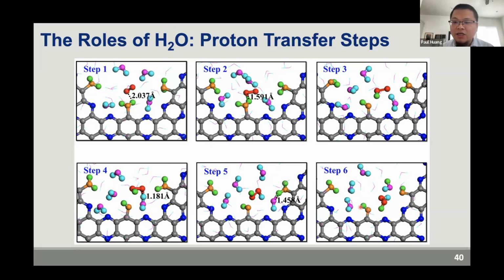And for that reaction, they have to involve 2 adsorbed water, and some local free water molecules will help to speed it up. And of course, I'm just showing you some snapshots from the exact trajectory, and we have identified 3-4 potential mechanisms, all involving this very nice proton transfer mechanism of water clusters. In the biology research field, this has been known for decades. And I think in chemical engineering, in chemistry, we have not paid close enough attention to that potential proton exchange chain. But this is extremely useful for this reaction we studied.